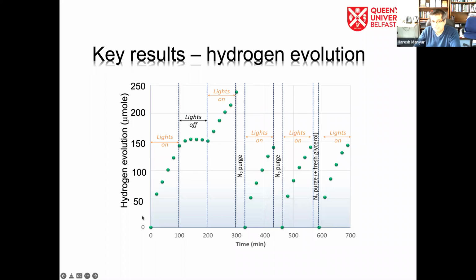You turn on the lights, you get hydrogen evolution, switch off the light, then no hydrogen production, and turn on the lights again, and you can see hydrogen production again. You can purge it in between with nitrogen, and you can see that again, hydrogen production comes on when you switch on the lights. So this is a very robust and stable catalyst and can be recycled and can be used a number of times. In fact, a master's student used the same tube for the entire 6 months of his project, and